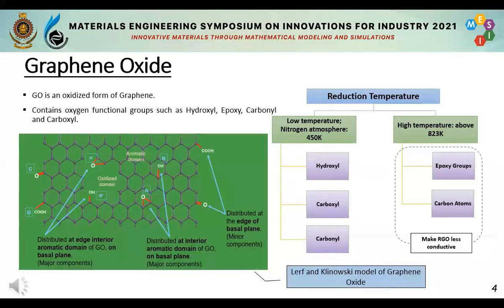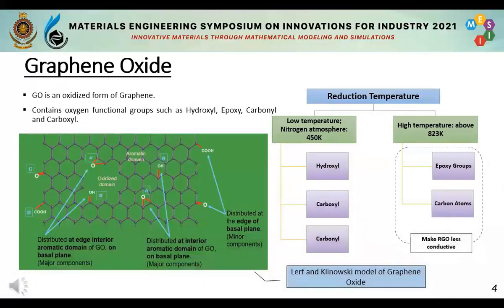Then we did a literature survey for the reduction temperature range. At lower temperatures such as 450 Kelvin, hydroxyls, carboxyls and carbonyls try to reduce. Then at higher temperatures, normally above 823 Kelvin, epoxy groups and carbon atoms tend to be removed. This removal of carbon atoms makes RGO less conductive. Therefore, we selected our reduction temperature range as 450 Kelvin to 823 Kelvin.